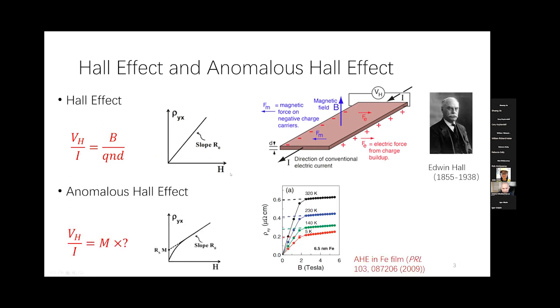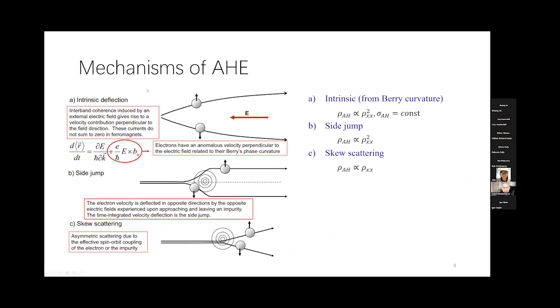After 2 years, he also discovered the anomalous Hall effect on a piece of iron metal. You can imagine the iron has a spontaneous magnetization, so this M may somehow replace the role of the external magnetic field. However, if you measure the anomalous Hall effect for a piece of iron or iron thin film at different temperatures, you see this anomalous Hall resistance is not dependent on the carrier density. So why and how the magnetization plays a role in the anomalous Hall effect needed almost 100 years to understand. Currently we understand the mechanism of the anomalous Hall effect as due to 3 different mechanisms.